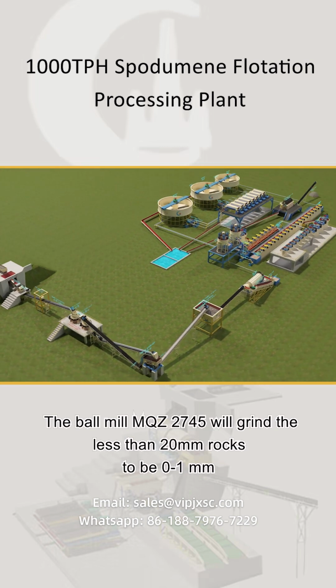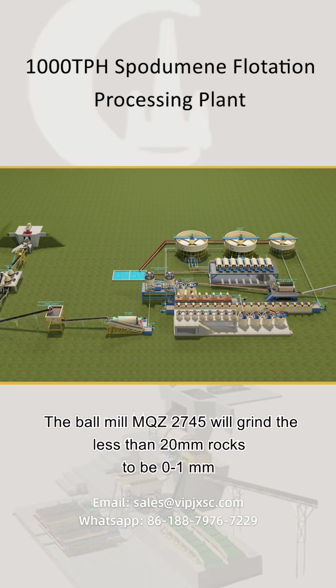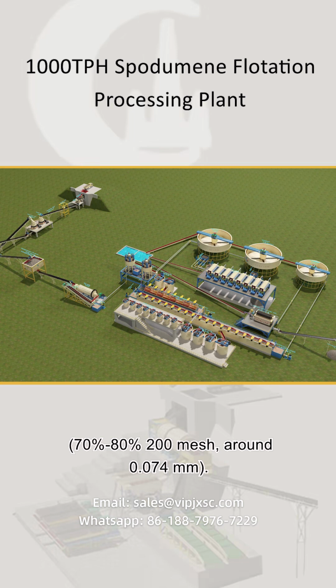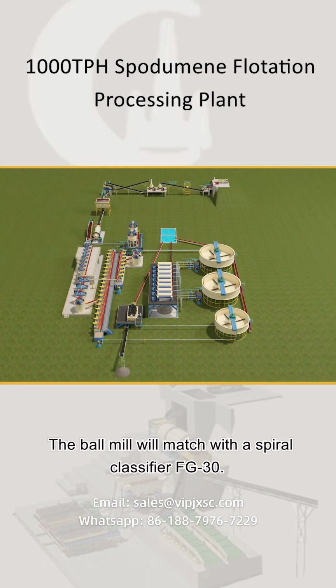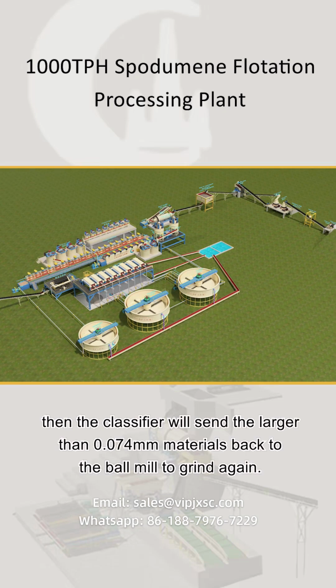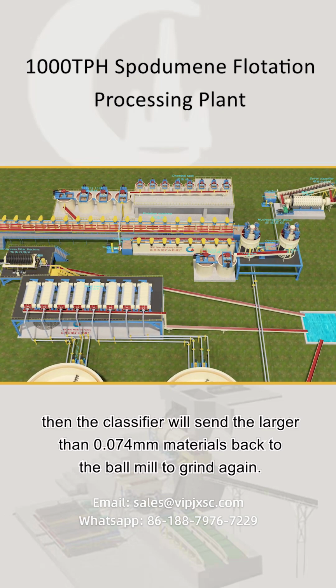The ball mill MQZ2745 will grind the less than 20 mm rocks to be 0 to 1 mm, 70 to 80% 200 mesh, around 0.074 mm. The ball mill will match with a spiral classifier FG30. The 0 to 0.074 mm materials will go to the classifier, then the classifier will send the larger than 0.074 mm materials back to the ball mill to grind again.